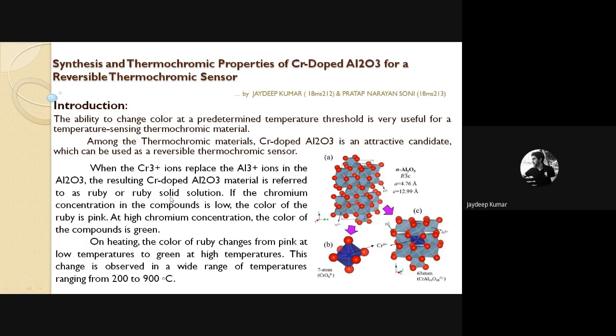So here what happens is chromium ions replace the aluminum ions in alumina, and that results in a compound that is known as ruby. When the chromium concentration in this ruby is low, then the color is pink, and at high chromium concentration the color goes to green. So on heating, the color of the ruby changes from pink at low temperature to green at high temperature. And this can be widely used in the range of 200 to 900 degrees centigrade.